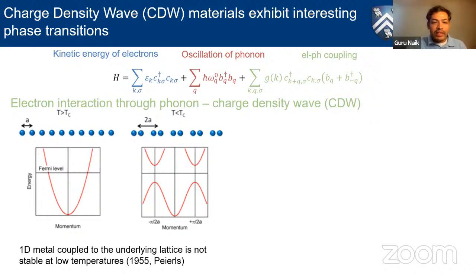It was predicted in 1955 by Peierls, who said a 1D metal simply cannot exist, by saying that if we had a 1D chain of atoms, then the atoms can simply undergo a slight lattice distortion such that they pair up, and that opens a band gap. That makes them semiconducting, and their overall energy reduces. So that's the most stable form. What he said was that the atoms which possess charge can undergo a slight lattice distortion, the slightest possible still, to open a band gap and then reorganize themselves.